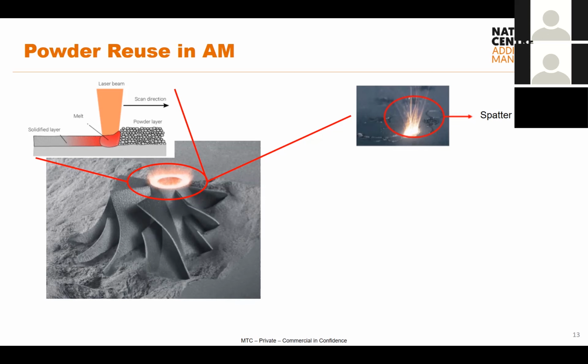And you can see them, they look like mini firework displays if you ever watch an SLM, a laser melting process in operation. Of course, what these particles are, they're molten, so they're very, very hot. So any residual oxygen in that container, those particles are going to pick it up. But also, in a similar way to the atomization process, those molten droplets, if they come in contact with anything such as a surface or other metallic particles, they're going to have deformed geometries when they freeze, when they reharden. And if those are too small to be taken out by the sieve, then those irregular particles will be present in your powder after you've recycled it. So you're going to have potentially bad morphology and locally high oxygen content in these particles. So that's bad news for your recycled material.